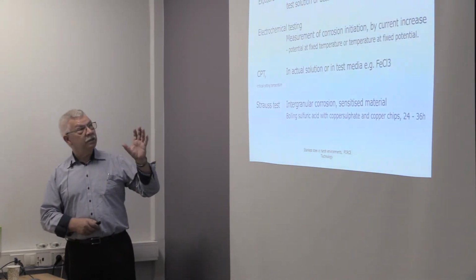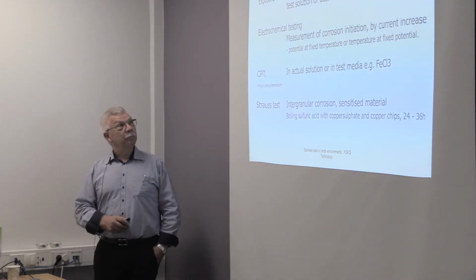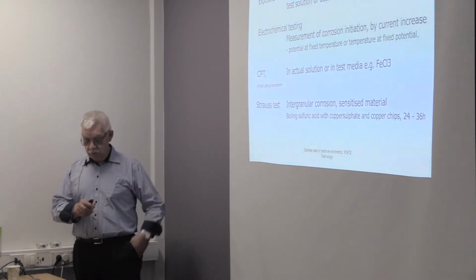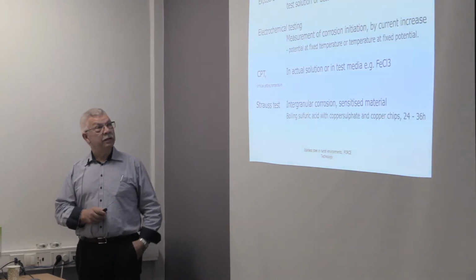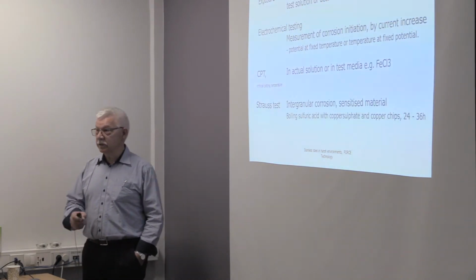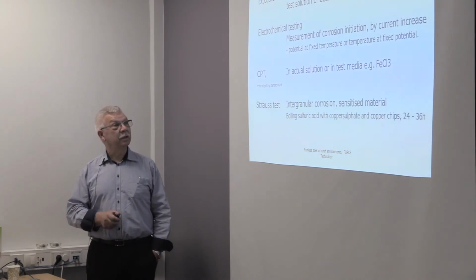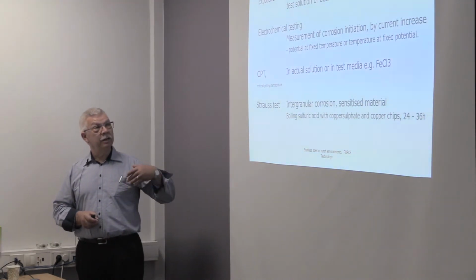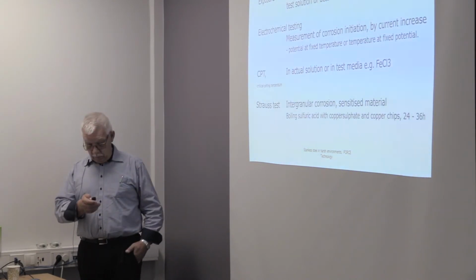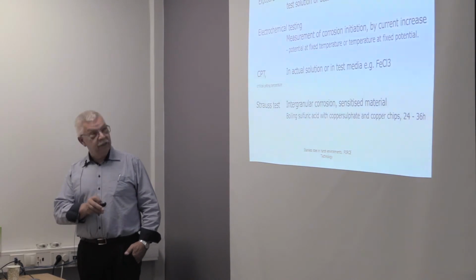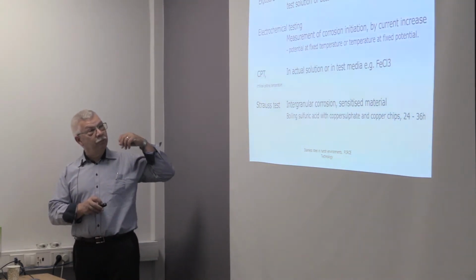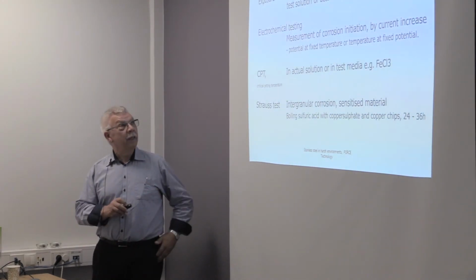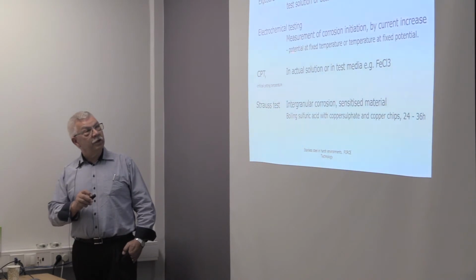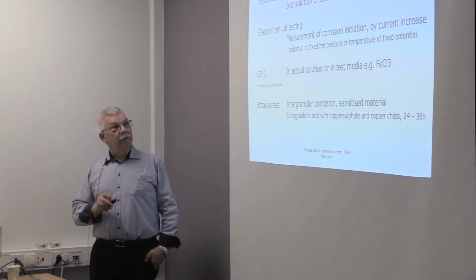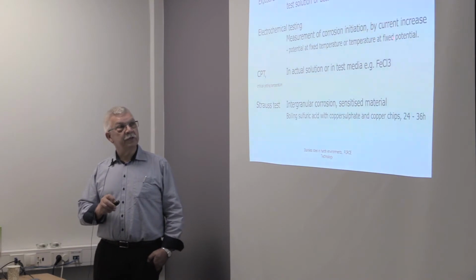But we can also make tests in the laboratory where we put on some potential to increase or to control the corrosion conditions, and that way find out where is our critical pitting temperature, where our crevice limit is, by controlling the temperature or the potential. The potential is the fuel for the corrosion, and we can measure the potential giving trouble at a fixed temperature, or we could find the temperature at a fixed potential. That's the possibilities.